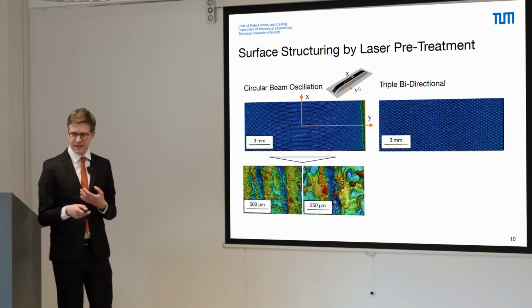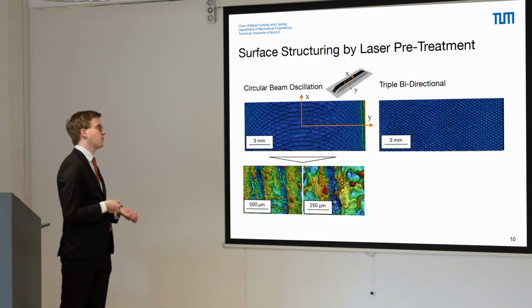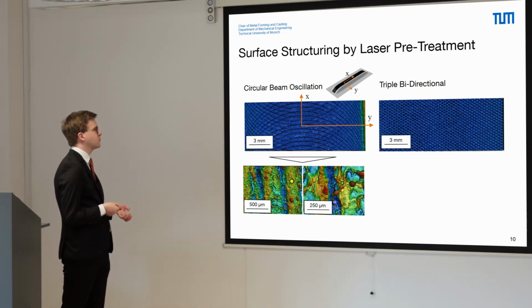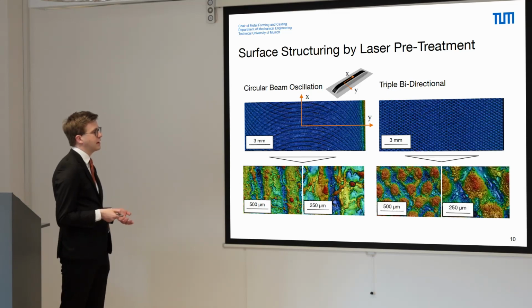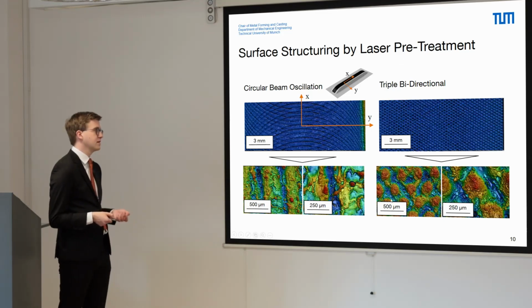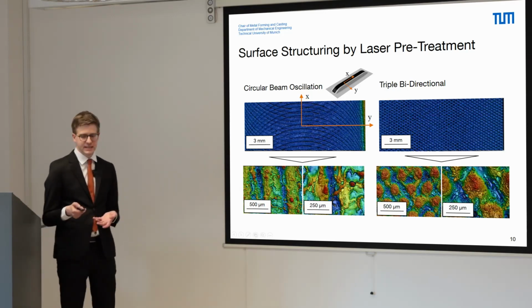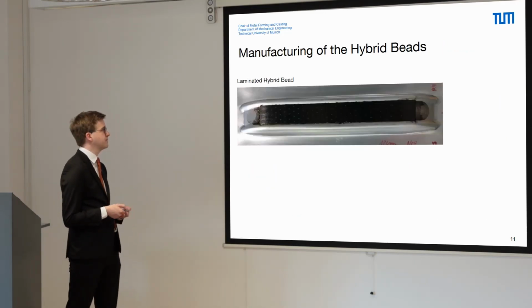On a microscopic level, we can see that there's more of a rounded structure, and here, for example, a molten and resolidified droplet can be seen. Similarly, here the trajectory of the laser generating these triangular-like structures for the triple bidirectional process, showing also this more rounded structure compared to the sandblasting process.